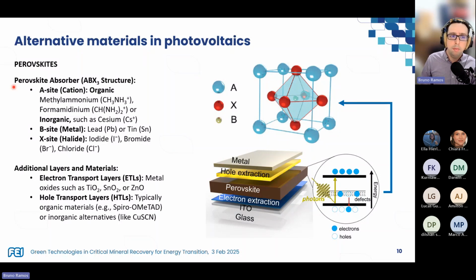And they have this shape here, the whole ABX3 structure, where A is the cation, and B is a metal in the center. And we have X, which are the halides here, shown in this picture. So the most common materials used in photovoltaics actually use organic cations, mostly methylammonium or formamidinium, which is quite good because we're using carbon and nitrogen, which is very widely available for us. But they can also use inorganic cations such as cesium. And on the metal side, we have lead or tin.